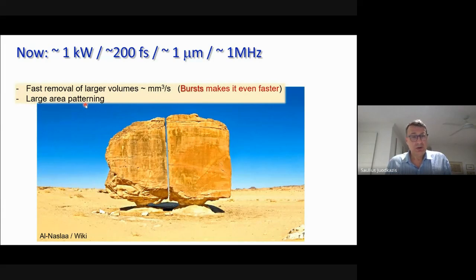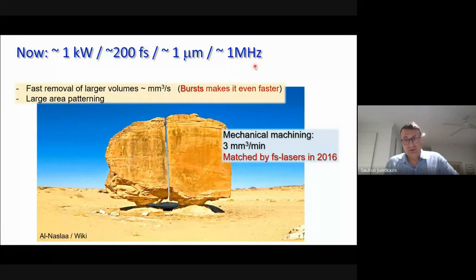So large area patterning, again, is not a problem anymore because we have high repetition rate and we can scan our pulses over the large area very fast. And in that Nature paper, which I mentioned before, in 2016, they actually reached an ablation rate of 3 cubic millimeters per minute. And this is the typical mechanical machining rate in high precision tool manufacturing. This is a rate which was already surpassed several times since that first paper. And now industry begins to look more seriously into ultrashort lasers instead of some mechanical cutting tools.